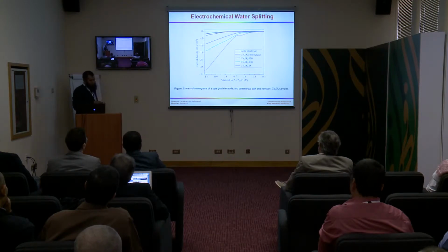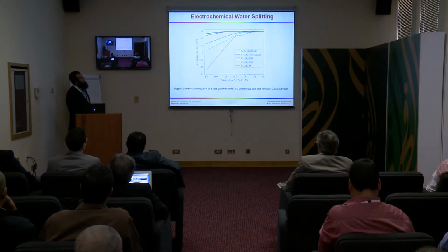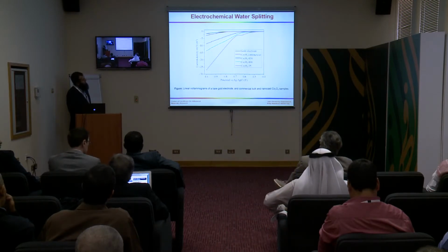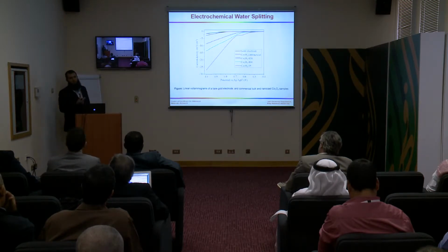When we applied these and studied the linear voltammogram, it is clear that the pure electrode shows no current density, and the commercial cobalt oxide also doesn't show much current density. But when we go for the mesoporous cobalt oxide, it gradually shows high current density at low overpotential. And in water splitting, the important thing is low overpotential. You have to split the water at low overpotential. Among these, the cobalt oxide grown on the silica treated at 35 degrees centigrade shows the highest current density at low overpotential.